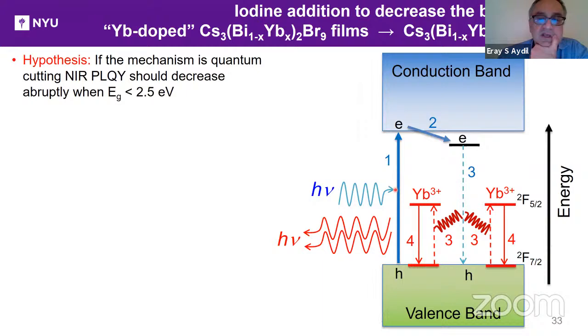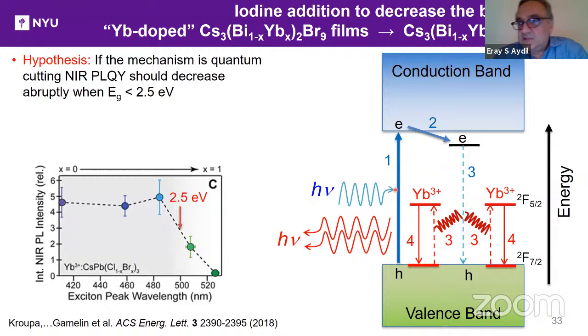So what we did next was to add iodine to decrease the band gap of the ytterbium doped films. So we're in essence now making the bromide iodide of the ytterbium doped cesium bismuth halide. And the hypothesis is that if the mechanism is quantum cutting, the near infrared photoluminescence quantum yield should decrease rapidly when the band gap is less than 2.5 electron volts, right? Because it takes 1.25 eV per ytterbium. And if one reduces the band gap to less than 2.5 eV, then one doesn't have enough energy to excite the two ytterbium in tandem. And in fact, that's what's observed with the cesium lead chloride material.